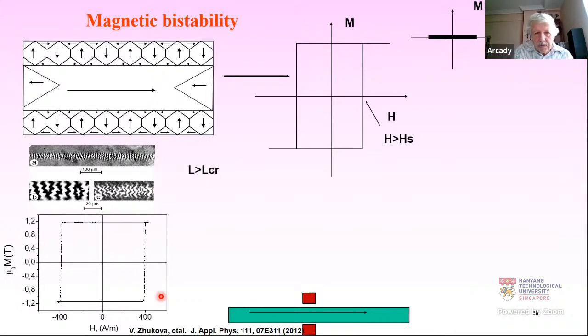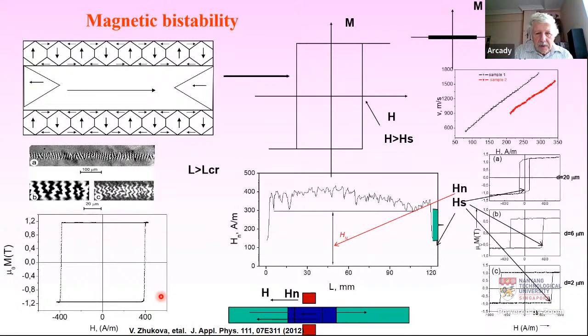And so I already mentioned that we can inject a domain wall in any place. Therefore, if the applied field is high enough, this single domain wall propagation, which I mentioned before, could be affected by other domains. And here, for example, you can see the nucleation profile of one of such samples. So this single domain wall propagation appears between the switching field, which corresponds to the nucleation field at the end of the sample, and the minimum nucleation field in the middle part of the sample. And this is the range in which we can get this almost linear dependence of the domain wall velocity on applied magnetic field.